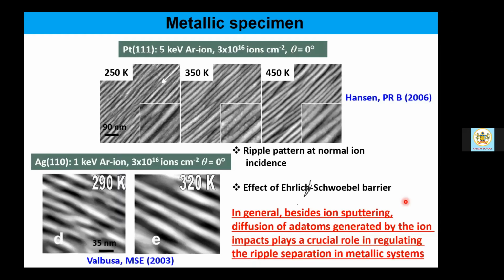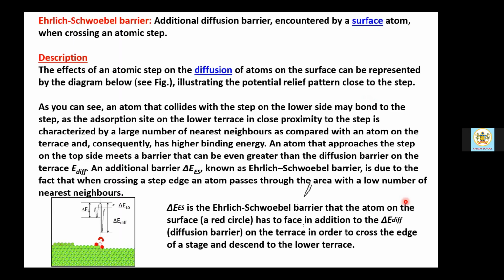So wherever we saw checkers pattern on germanium, we saw it at high temperatures, and these beautifully ordered ripples on metal surface also take place at elevated temperatures. And this can be attributed to the Ehrlich-Schwoebel barrier, which actually is a very popular term, or energy barrier that is faced in case of molecular beam epitaxy related growth. So additional diffusion barrier that gets created or encountered by a surface atom when it crosses an atomic step. Okay, so it's kind of step diffusion.